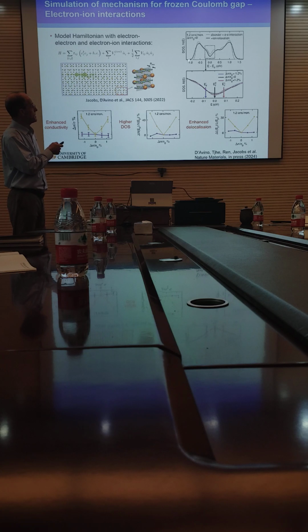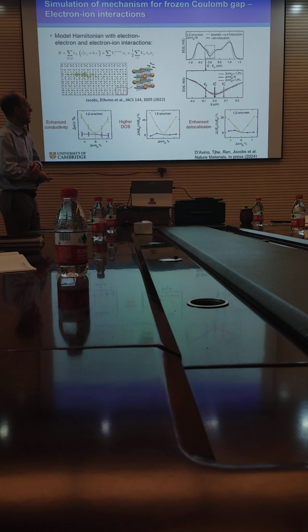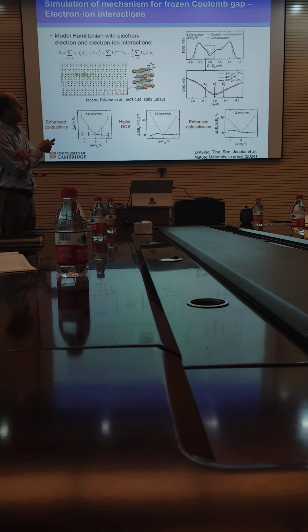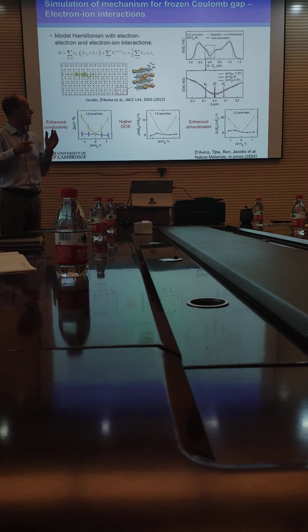And when they then calculate, they can calculate the density of states. This is just a single band, the HOMO band. And you see that at the Fermi energy, you see this Coulomb gap. You see this depression of the density of states due to the electron-electron interaction. And what's interesting is they've done this calculation under two conditions. The gray line is the condition where you take into account the disorder in the transfer integrals and so on, and you take into account the electron-electron interaction only. Then you get a Coulomb gap suppression as you see here. If you take the electron-ion interaction into account as well, if you allow the ions to relax a little bit when you change the electron density, then this Coulomb gap becomes deeper. And that makes sense. If you allow ions to relax, that will tend to localize the charges more strongly. And the fact that we see this Coulomb gap deepening is consistent.